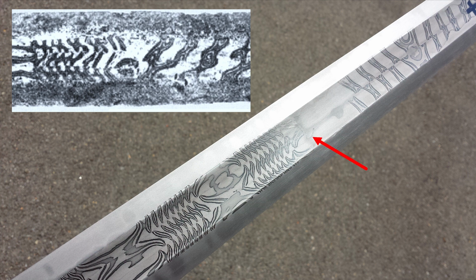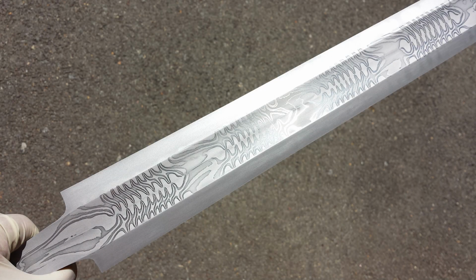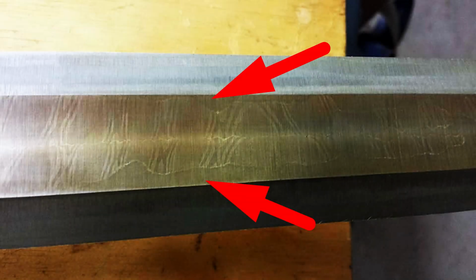It doesn't look like the original, but the dimensions of the twisted and straight sections weren't too far off. And what happened here taught me of another mistake I made that would need another approach to correct. When you grind off too much, you end up showing what is underneath. I had sandwiched a layer of plain 1095 steel at the center of the blade to figure out the correct amounts to grind off the surface without going too deep. If I happened to grind into the plain 1095, I was going too far, which is exactly what happened.